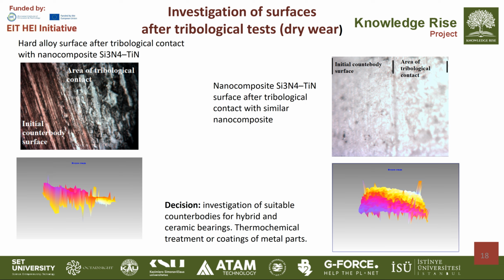The figure presents a comparative study of surface condition before and after tribological tests of hard alloy and silicon nitride based nanocomposites under dry sliding condition. The objective is to analyze wear mechanism, surface morphology, and potential of ceramic composite for bearing solution. The image on the left shows a hard alloy counterbody surface that has been subjected to dry sliding contact with the silicon nitride nanocomposites.